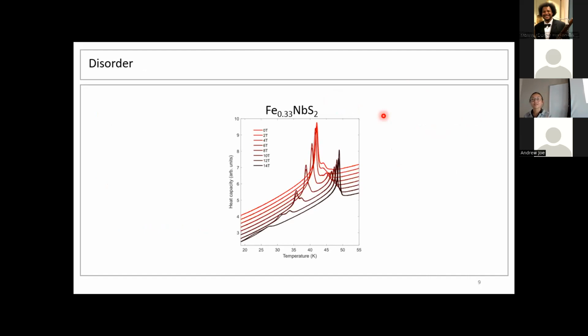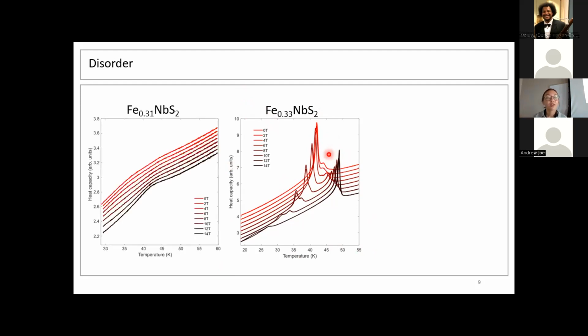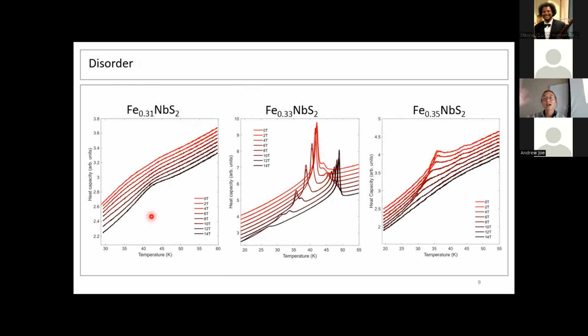And something that I'll mention is that if we look at other measurements of our perfect and then our two imperfect systems, there's basically no measurement that we at least typically do in our lab that has such a qualitative difference between these systems. So for example, this is heat capacity as a function of temperature. Basically these peaks are just showing that there are these very nice sharp phase transitions. If we go to an iron deficiency, the locations of those peaks move a little bit, although it's hard to see. If we have an iron excess, the locations of those peaks also move a little bit, although it's hard to see because the peaks themselves are really suppressed.